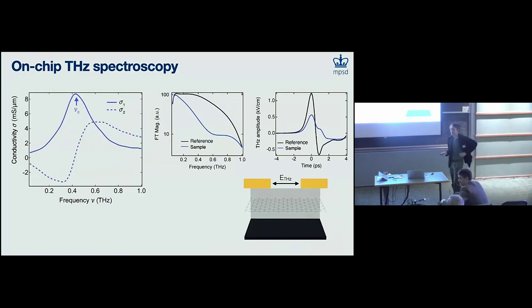Sorry, James, what is the distance between the sample and the source in picoseconds? Because I'm thinking about reflections. Yeah, reflections. We engineer it to be on the order of 20 to 50 picoseconds. The circuits are many millimeters long, which is intentionally to reduce reflections. All of that is very carefully considered, because once you get a reflection, you're sort of stuck. That's the end of your bandwidth. So there are a couple of millimeters between the terahertz source and the sample, then another few millimeters until the detectors, to delay these reflections for as long as possible. Okay, good technical question.